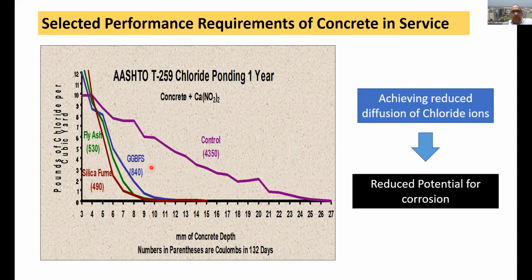This is the profile of chloride. Chloride was placed at the top. So here is the depth of concrete. So this is the surface of concrete, and we are walking through the depth of the concrete. Chloride was put here, and if you look at control concrete, chloride was able to get through very rapidly through this concrete. But the minute we added some blast furnace slag and fly ash, you can see that now it is finding it tougher and tougher to get through concrete. So we can engineer this material to cut down on the penetration of chloride ions in concrete.